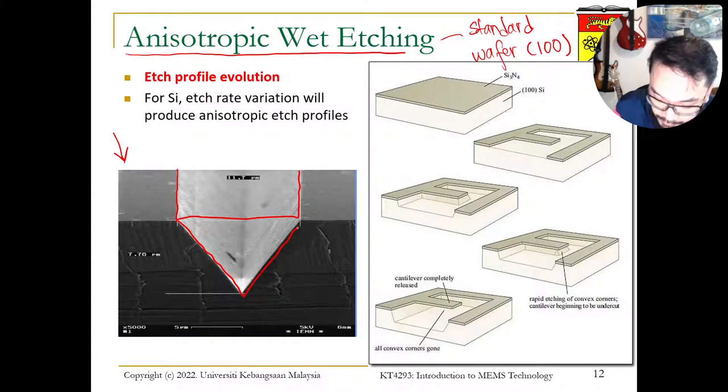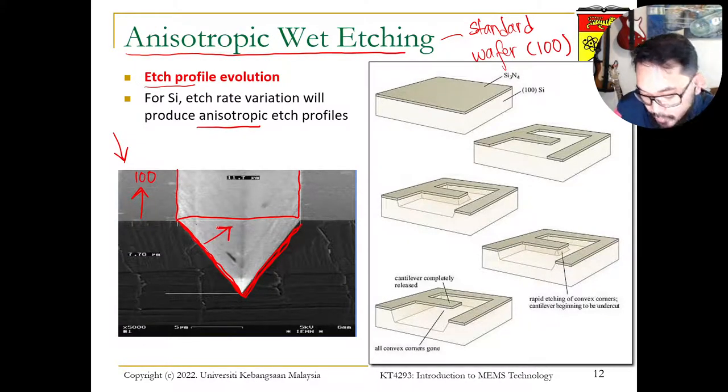That means the etch profile evolves until you get an inverted pyramid like this. We call it anisotropic because it follows the shape of the crystal plane. Which plane? The surface here is 100 because it's a 100 wafer. When we do the etching, the exposed plane here, the V shape, is the 111 plane. We will see why the 111 plane is exposed and the etching profile follows the 111